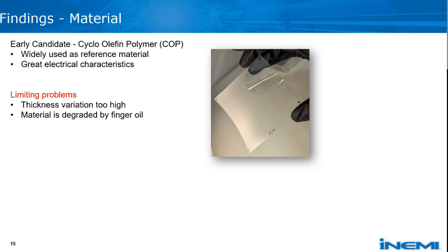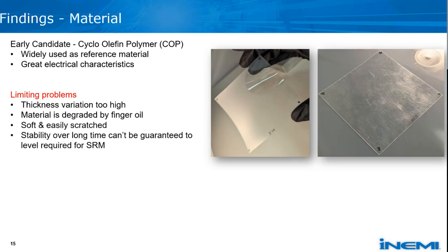So the typical thickness variation for these materials just was not good enough, and we had no way to really make them any better. We also found that these materials were likely to be degraded by finger oil. So they're sensitive to material changes with oil, and that was a concern for the longevity and stability of an SRM if we were to use these materials.